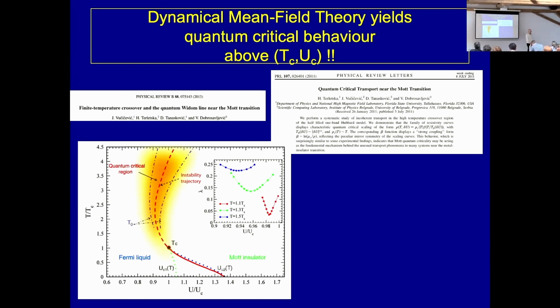Well, it turns out that this is apparently absolutely not true, and there is something really fascinating happening here. We've known for a very long time, since the early days of the DMFT equations, that there are very interesting crossovers here. We now know that these crossovers are also associated with things happening in the electronic compressibility. This has been called the Widom line. It's a long story that I'm not going to describe in detail. But the thing I would like to focus your attention on is that in this regime, it has been shown, just by solving the dynamical mean field equations, that the conductivity ratios seem to obey some sort of quantum critical scaling. This is very surprising because we are at relatively high temperature, not that high, but like 2 or 3 times TC, and certainly not close to T equals 0.